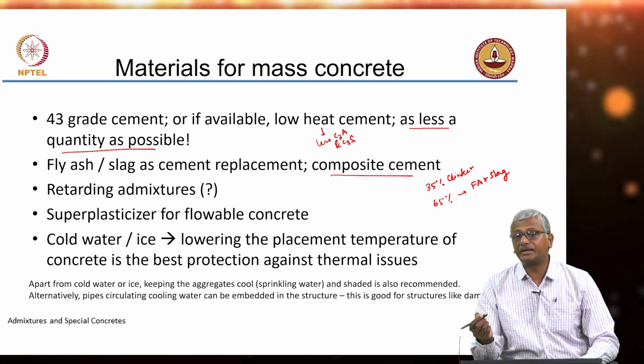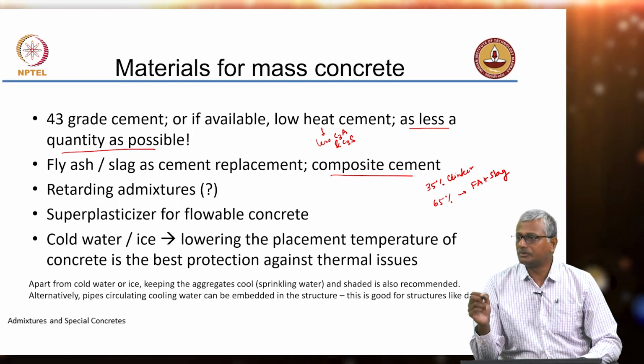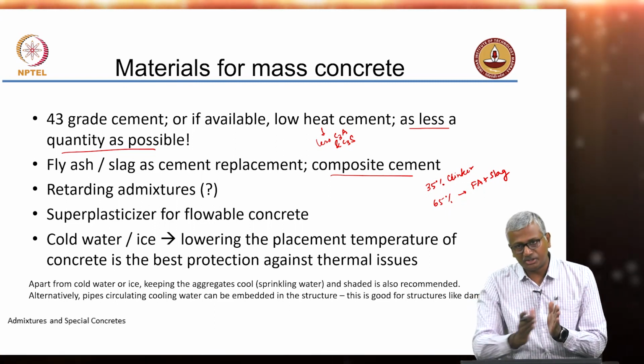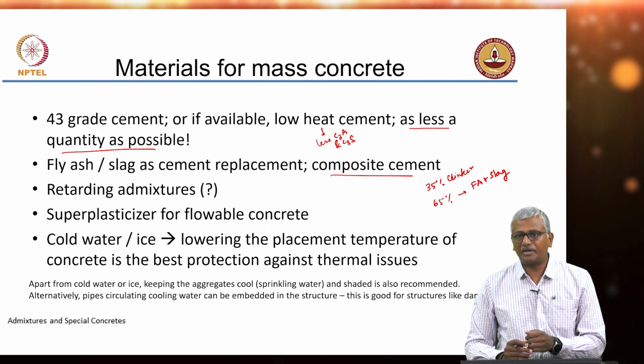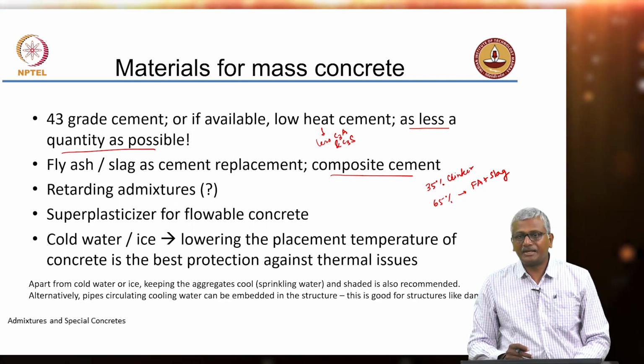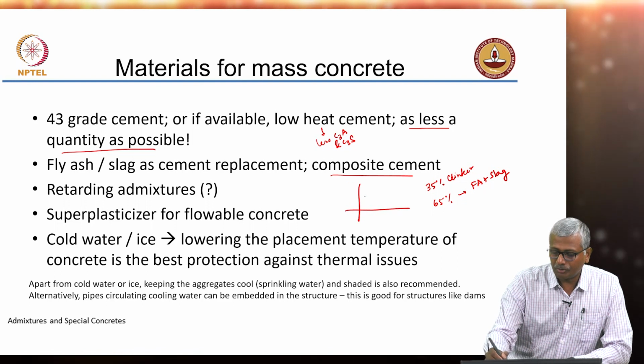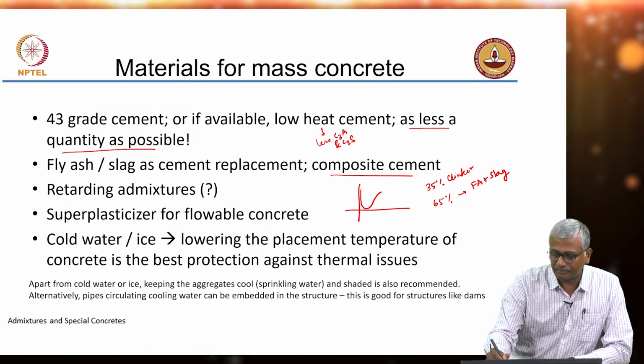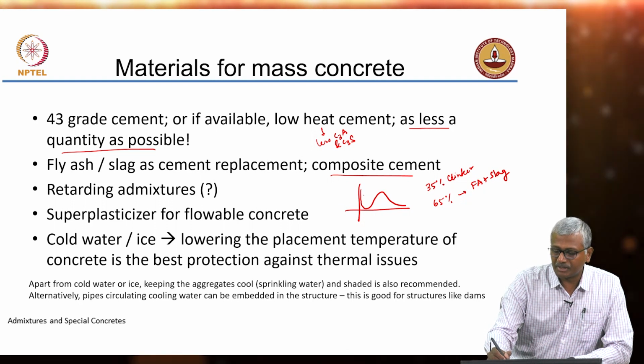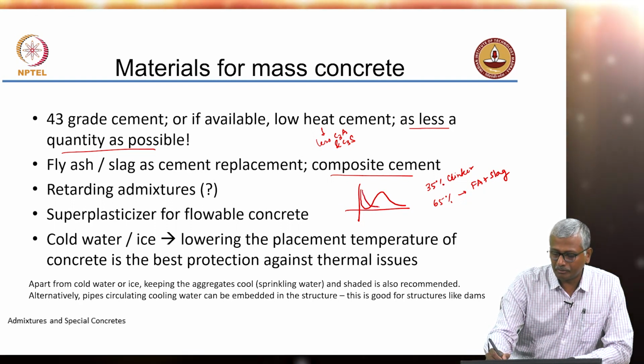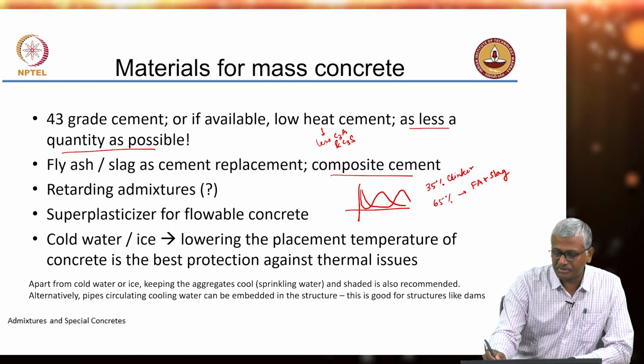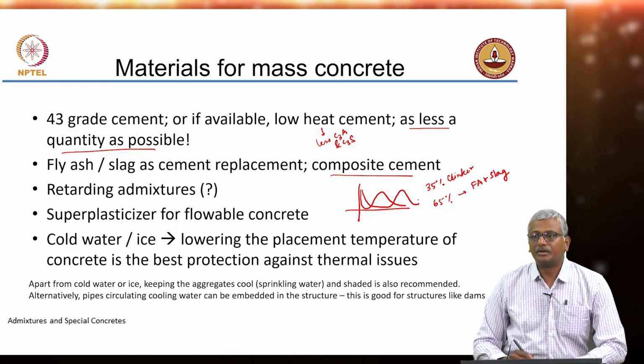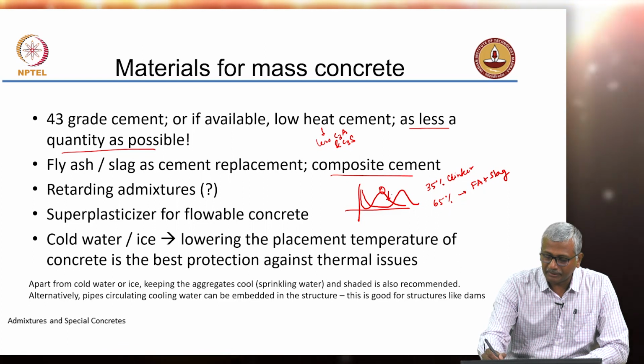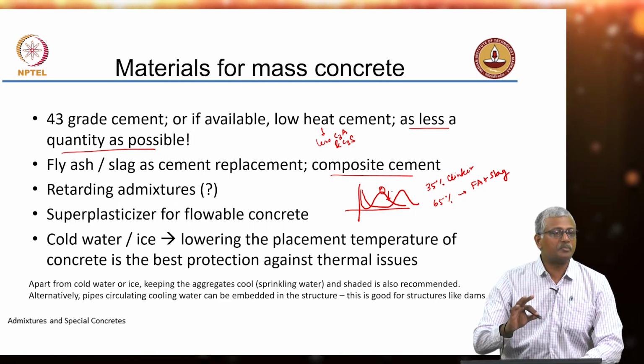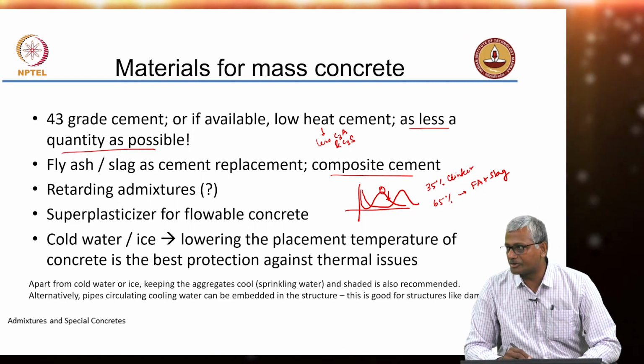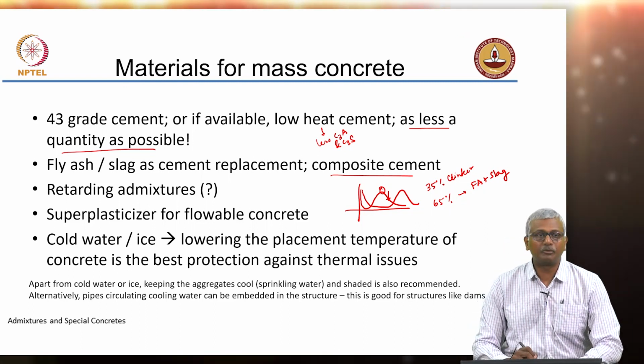You could use retarding admixtures, but you need to be careful because sometimes the retarding admixtures may just push the dormant period. They may not overall reduce the heat rate. So, what I am trying to say is, if your heat rate curve looks like this, your use of retarding admixture may simply prolong this and you may still get the same peak. Okay. So, what you need to do is reduce this peak, and with retarding admixtures you may or may not get that depending upon the type of admixture. You will definitely get that with the help of fly ash.